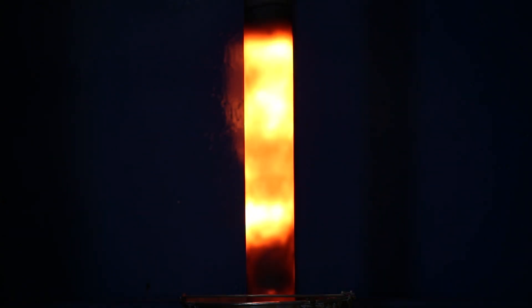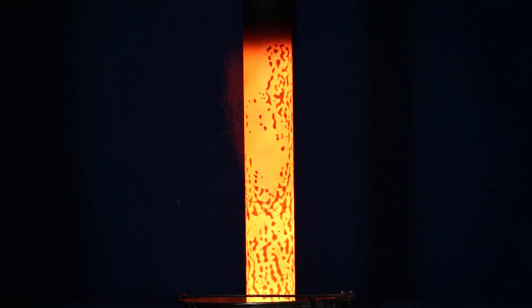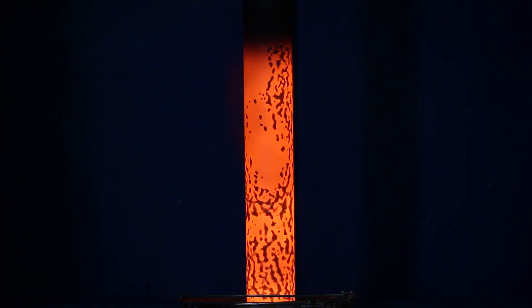The traditional problems with using bismuth-based alloys downhole is the ability to melt them. Everybody that's tried it before us has been using electrical heat. There are lots of advantages to electrical heat — you can turn it up, turn it down, increase the amount of heat generated. Unfortunately, it takes an awful lot of power down the wireline to produce that heat. We've been experimenting with using thermite, and we could just see the reduction in time from six hours to melt the alloy to literally a couple of minutes.